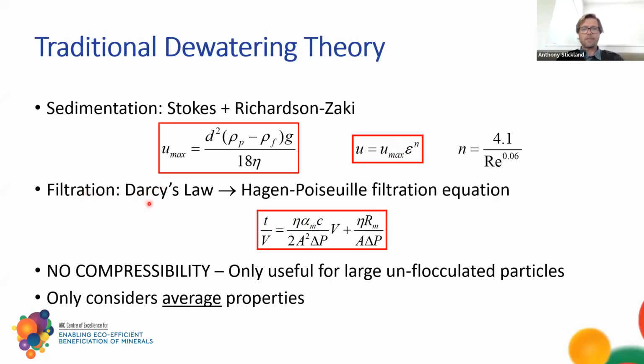On the filtration side of things, I typically use a packed bed description of the filter cake that's building up and apply Darcy's law across that filter cake. Because the filter cake is building up as a function of time and directly related to the speed at which you're going through that filter cake, you end up with what's called the Hagen-Poiseuille filtration equation, which says that the inverse flow rate, t over V, is equal to the viscosity times the specific cake resistance, and I'll come back to this, multiplied by c, which is the cake solids mass per unit volume filtrate. It's a concentration, divided by 2 times the area squared times the pressure drop, multiplied by the volume of filtrate, plus the viscosity times the membrane resistance Rm divided by the area divided by the pressure.